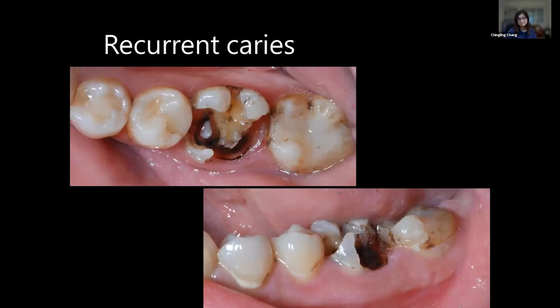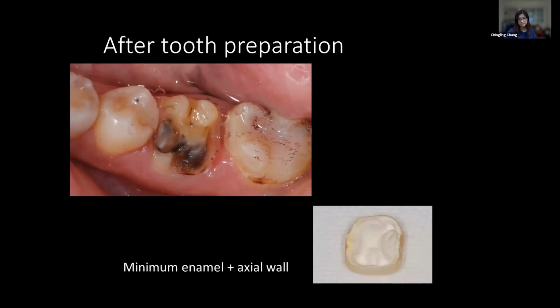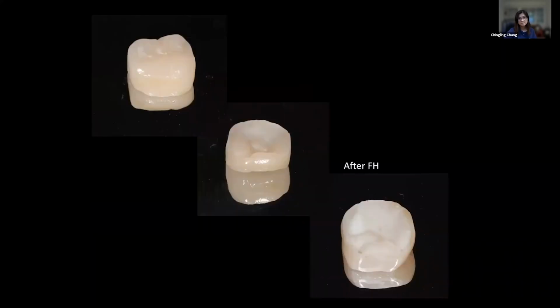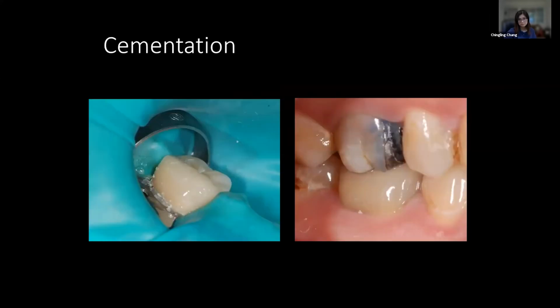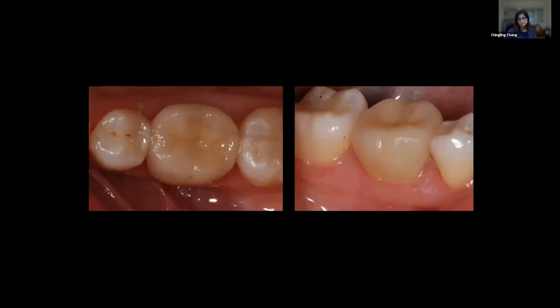Very similar case, big caries, and still we don't have much structure, especially on the buccal cusp. So we preserve the enamel, and we try to gain axial walls in our preparation. And we had the crown in the mouth for a month or two. The temporary cement was still remaining, so we know the design works. So this is the bonded restoration we provide. I think it relies on the bond strength, and also relies on the tooth preparation. This is after cementation. The crown has lasted for 10 years too.